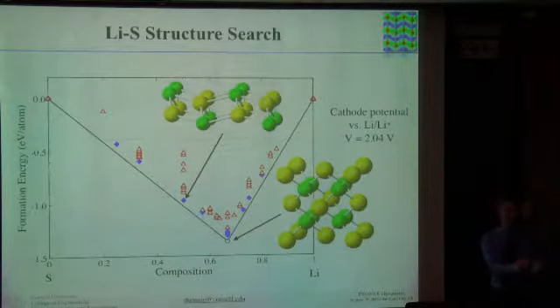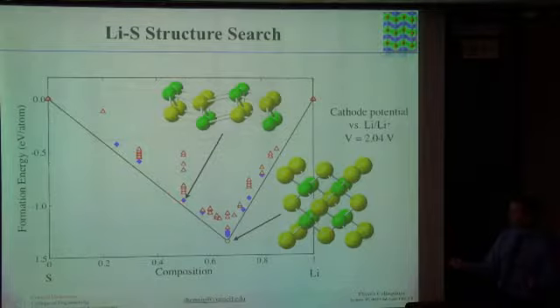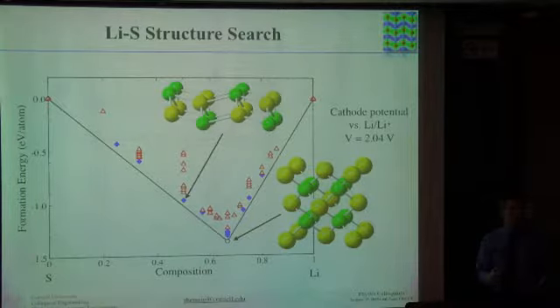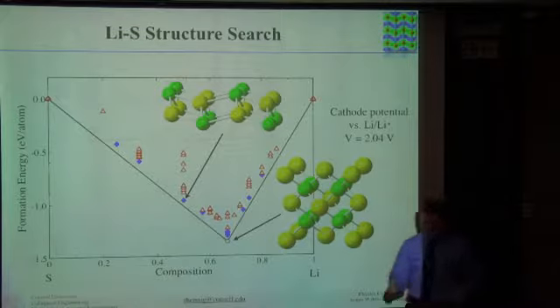It's got to be 50-50 lithium sulfur, 50-50. And that's pretty much the end of the paper. So we thought, well, let's look at it. Maybe there is something. And there's something somewhat close to the convex hull, but it isn't quite stable. So we're still not sure if that's what they found. We're currently working with experimentalists trying to go through the lithiation of sulfur and see if they can see some signatures of some 50-50 compound like that, maybe at higher temperature.